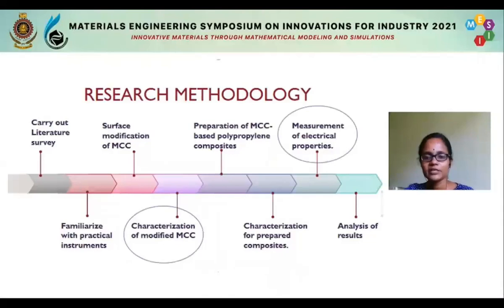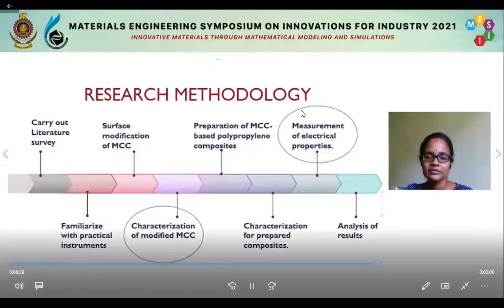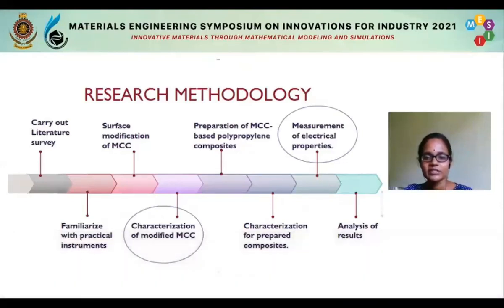In our methodology, I want to mention a few things. For the characterization of MCC, we use three methods: FTIR, SEM analysis, and hydrophobicity test. And we measured the electrical properties with different compositions and different frequencies. Parameters which we measured in the LCR meter were dissipation factor and capacitance. The electrical properties which we considered in the research were dielectric constant, dielectric loss, and AC electrical conductivity.